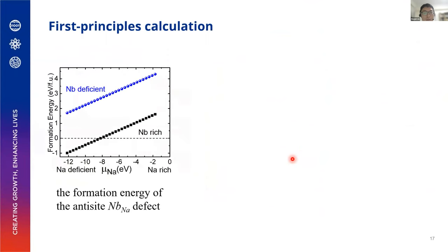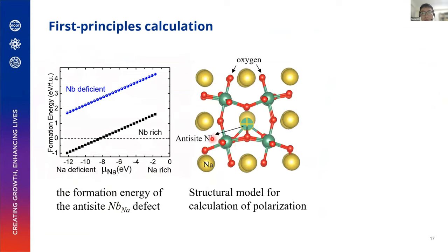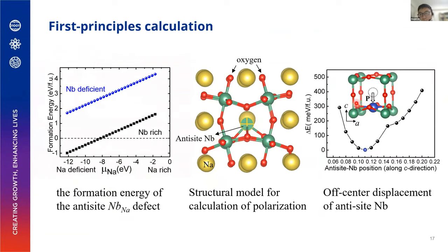Okay, then we have some theoretical simulations to show that with the sodium deficient condition, you have the formation of this kind of defect. And then, similar to the story we showed in strontium titanate, the niobium atom is much smaller than sodium. So once you have this niobium atom at the sodium site, the low energy position is actually not at the center, but shifts in the unit cell. So this contributes to the local polarization in the films.